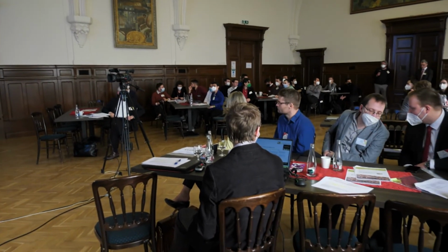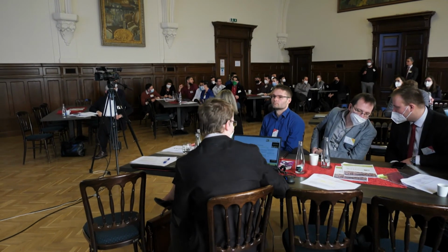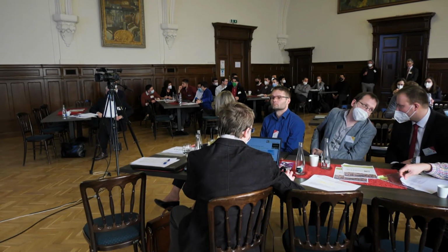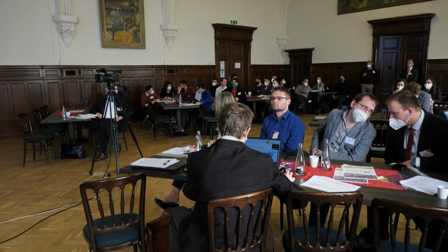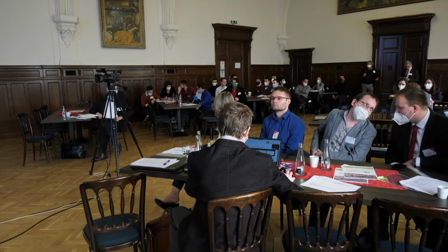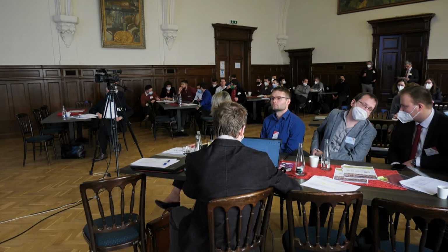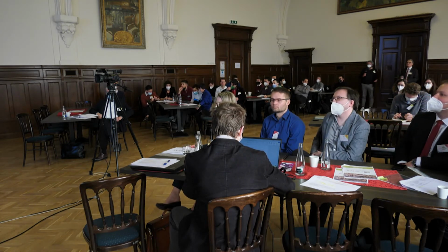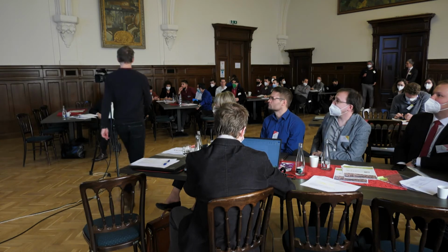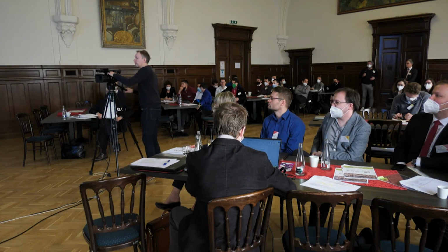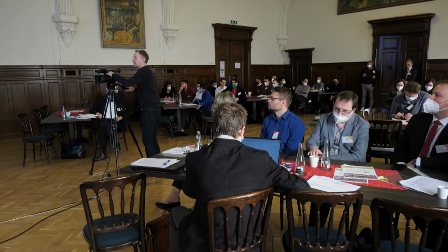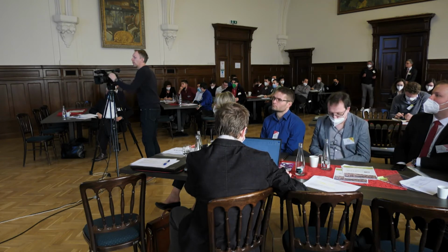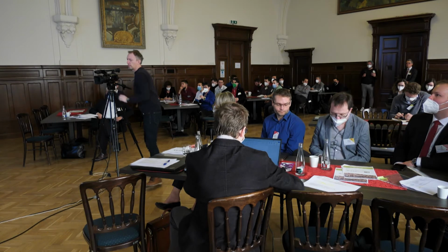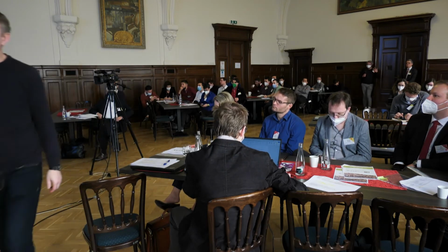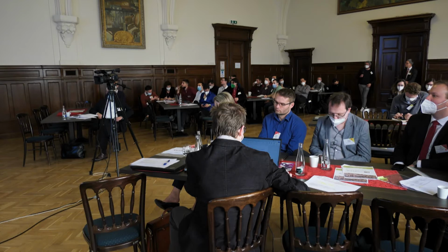Yeah, it's Peter. So I'm very happy that you take a more controlled electrode, because a felt is a very bad electrode for CV, because you have different diffusion regimes in the felt, porous diffusion, so you cannot really judge CVs from felt. It's really difficult, you can't do it. So in your microelectrode you have definitely more control over the experiment and can get really data out of it, and you can also define surfaces, which allows you more information.